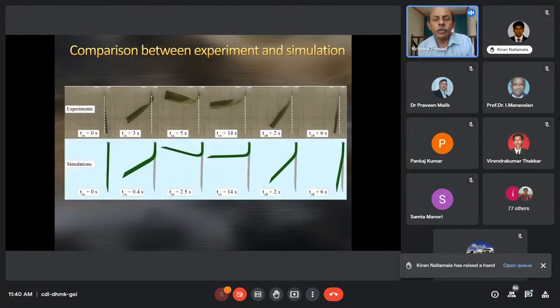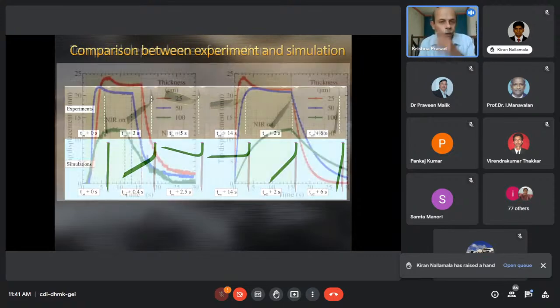So I'm going to show quickly a couple of slides here of the comparison between the experiments and simulations. The top are the freezes of the films, the actuating films that we have made of the liquid crystal polymers at different instants after the NIR is irradiated onto the system. And the same has been simulated with the kind of model that I showed. And lo and behold, we see that the simulations can effectively describe, even in a qualitative fashion, how the system gets energized, temperature rises, and gets actuated to different positions. So simulations copy the experiments very well, showing us that the modeling has been quite effective.